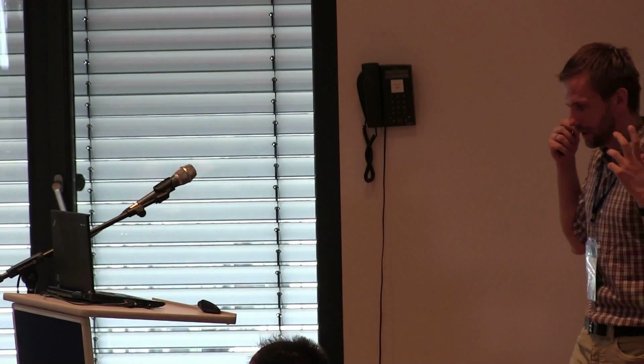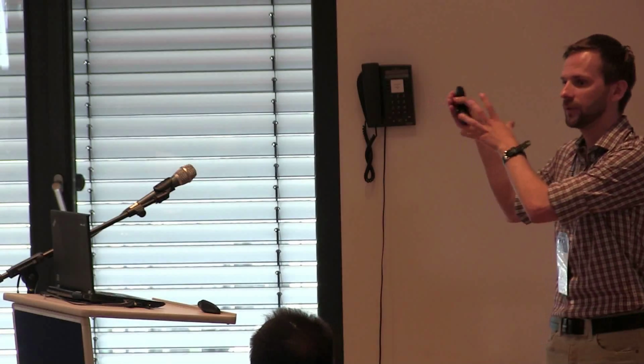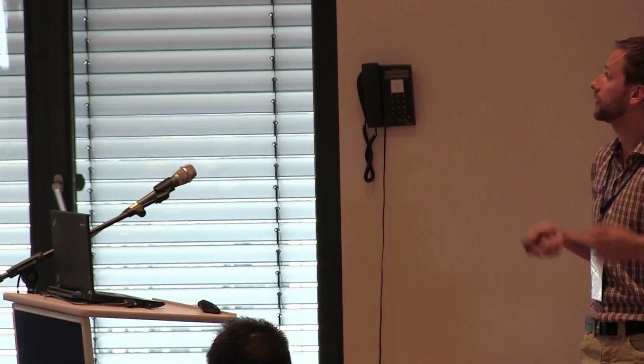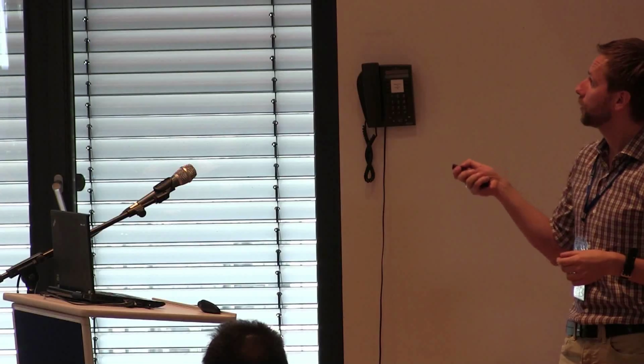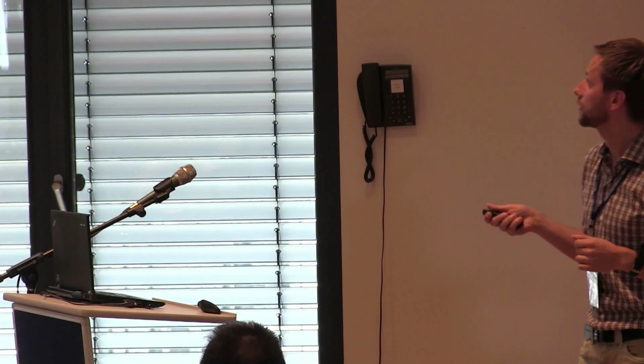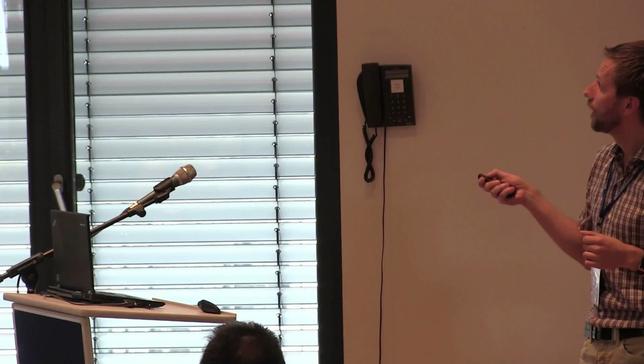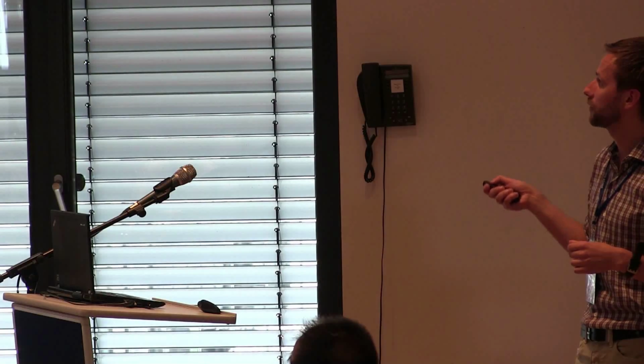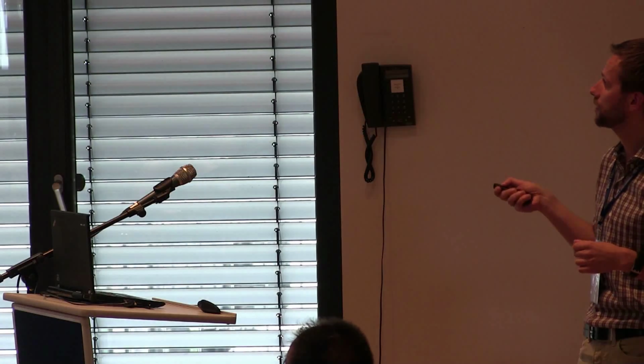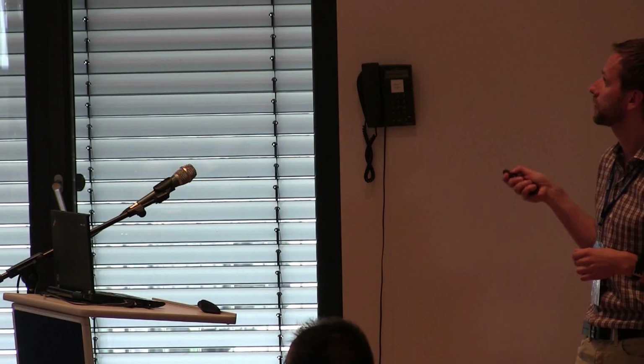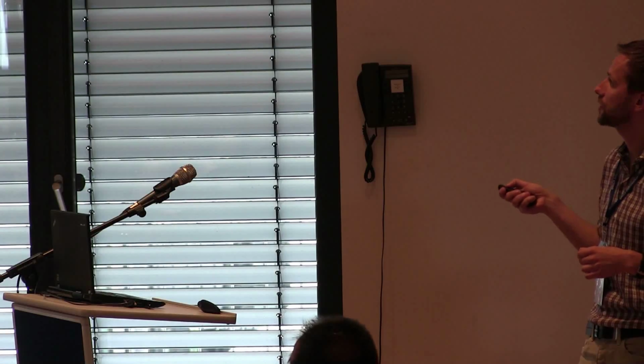Okay. The important thing, the next slide will be the qualitative explanation of why graphene becomes resistive when you increase the electron temperature. It is that for the hot electron gas, the chemical potential must decrease in graphene. Yeah, so just bear with me for the next couple of slides, and then you'll understand why. The population density function, as you know, is a product of the Fermi function, which is a step-like function, and then the density of states of the material. So if you multiply these two functions, the step-like Fermi function with density of states, which in graphene is linearly increasing with energy, then you will have such a triangular function, which is the population density.